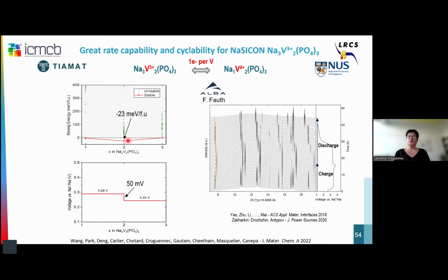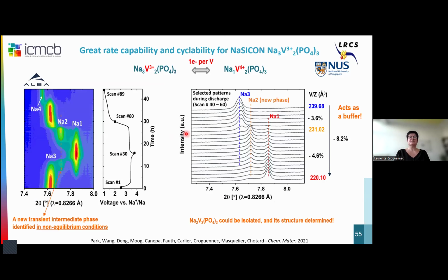So of course, we were interested in order to prospect these reactions. And first we prospected literature, and we saw that we had some already intermediate phases in some results reported by other colleagues, but not mentioned and not analyzed. And in fact, we did these experiments at synchrotron ALBA.